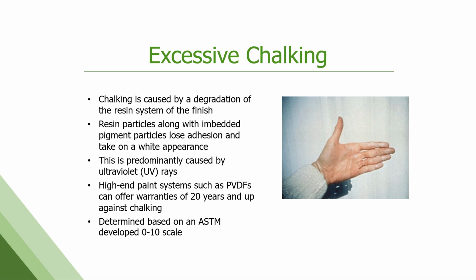The high-end paint systems will offer warranties of 20 years plus against chalking, that this won't happen. There is an ASTM test for it on a scale of 0 to 10. The 10 being the best, the higher the number, the better. If it's a 10, it's got no chalking. That's how the chalk scale works. This is not something we see very often anymore.